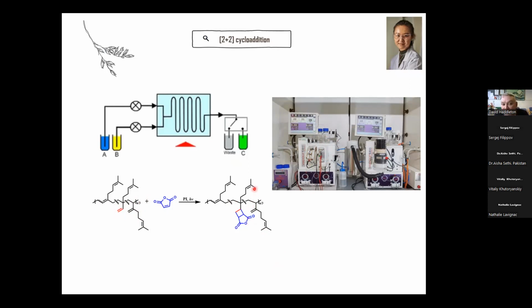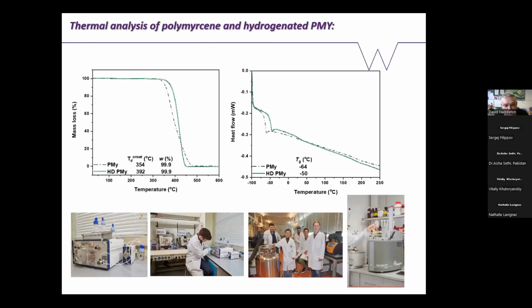And then we hydrogenate it all in flow. So what we've now got here is a flow hydrogenator, and this is Will actually. So we've got those two systems there. So we do the polymerization, then the photo functionalization, and then it flows into the hydrogenator. Hydrogen's made electrochemically, and then we fully hydrogenate out all the double bonds. And then we have a benchtop NMR. We flow it through the NMR at all the different stages, and at every stage, we get optimization of the reaction in flow.